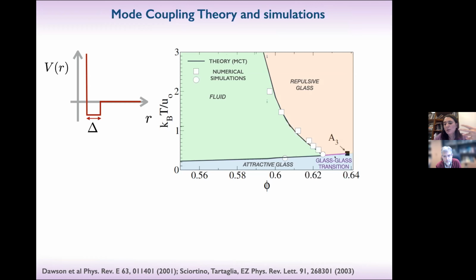I mean, the problem to investigate this is that you are out of equilibrium, so you have to monitor the age independence. So it's a little bit tricky, but our evidence is that basically with some time it will tend to go to the glass. And then we studied this also with Wilson Poon much later, that there is actually another problem: for this attractive glass line, like in glass formers like Lennard-Jones, the hopping mechanism which destroys the glassy phases is much stronger than in the topological cage.